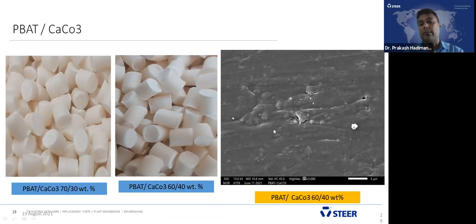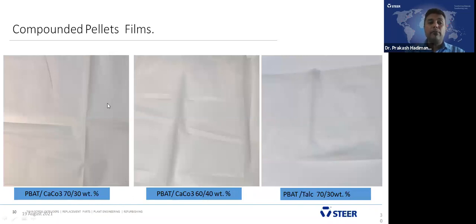particles in the calcium carbonate, and that shows lower mechanical property. We got better distribution and dispersion, but still the particles are bigger in the calcium carbonate. And we did the blown film for PBAT, calcium carbonate, 70-30 combination and 60-40 combination, even in talc. No challenges we observed, and it was very smooth running of the carry bags and no black specks, and dispersion